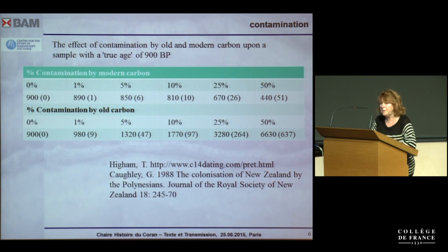If you have parchment with an addition of so-called old carbon, or if conservation materials involved old carbon, you would have a completely different age. So one of the other important things that we pursue as a material science group is to analyze whether the pieces to be dated are contaminated or not, and to help those labs to clean the organic matter better.